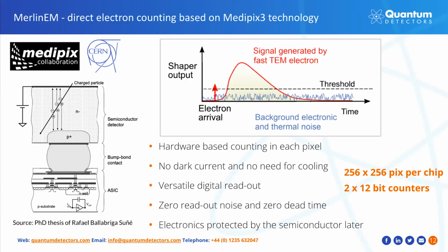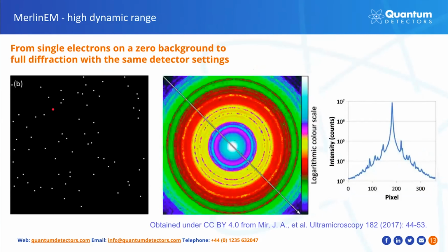The last but not least point on the slide is that because the detector is covered by this thick semiconductor, in our case silicon layer, we don't risk any damage to the electronics even when imaging central diffraction beam at 300 keV. To demonstrate the possibilities of direct hardware-based electron counting, I have chosen a couple of images from publications by Jamil Mir. The first image shows single electron events captured on otherwise dark frame, demonstrating single electron sensitivity of MerlinEM detector. The second, more colorful one, shows diffraction from a polycrystalline gold specimen utilizing 24-bit counting depth.